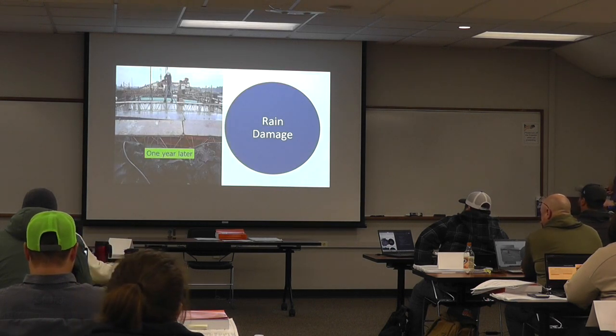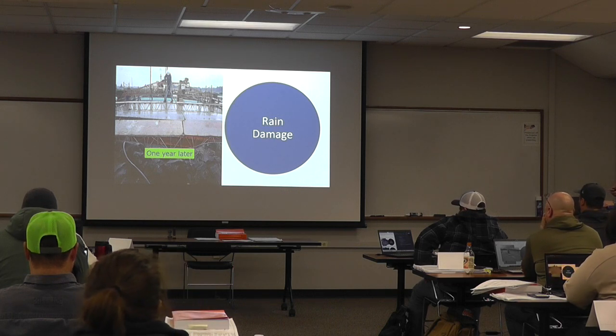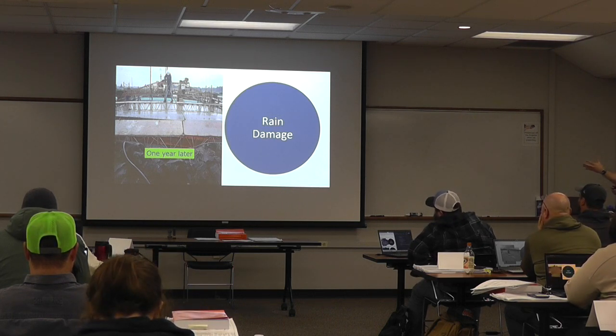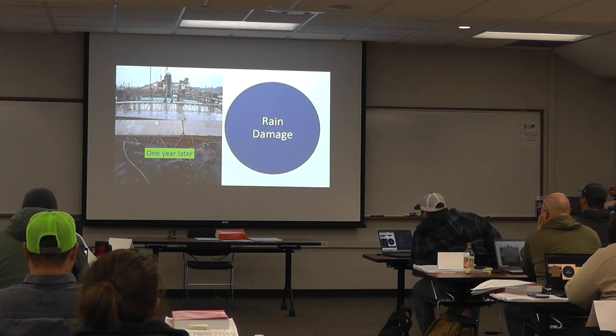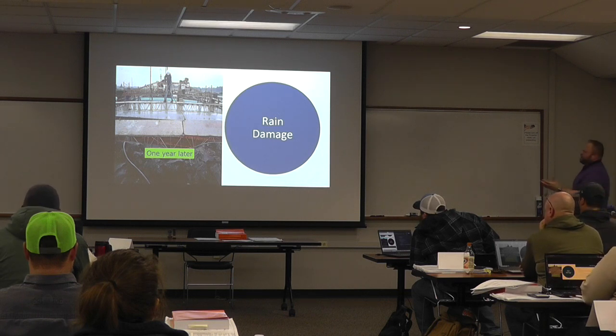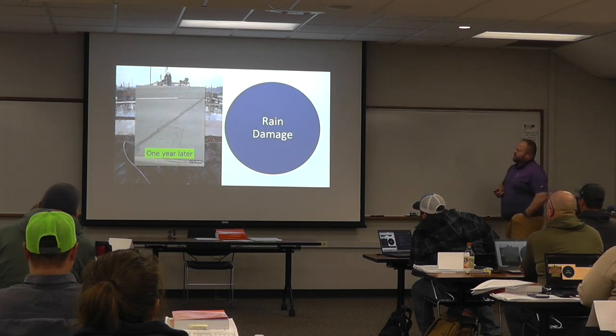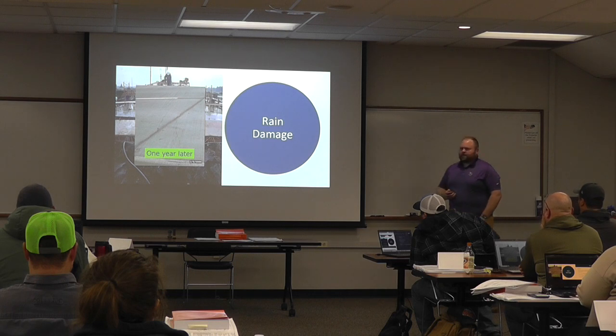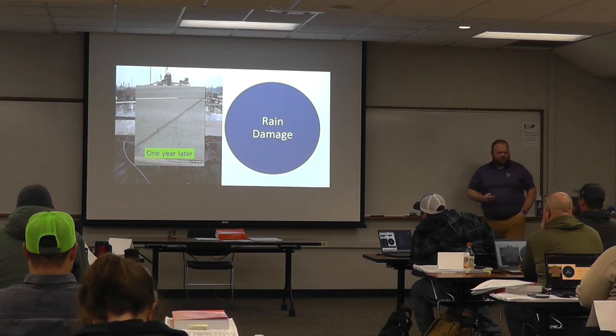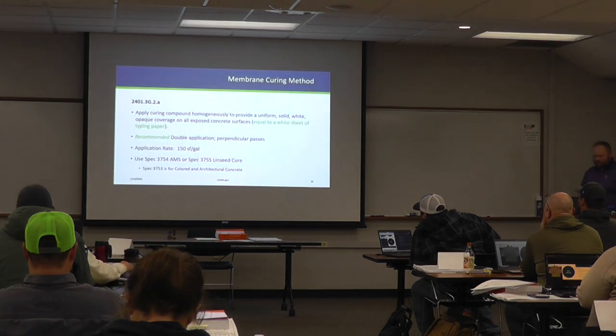Here's one where I'm not quite sure how this happened, but they were placing the concrete, and obviously it looks really wet. Sorry, a freak storm happened or something and it started raining. So this is that concrete during placement, and then 1 year later we've got these cracks that are forming from that rain damage. So we want to try and avoid that.